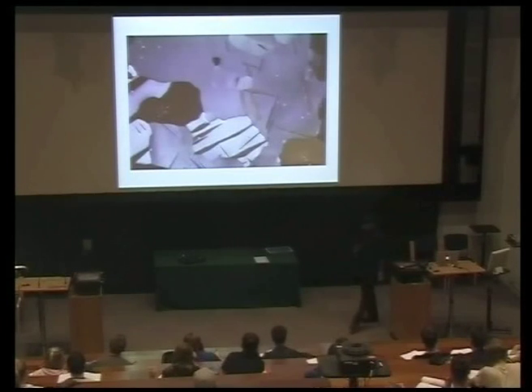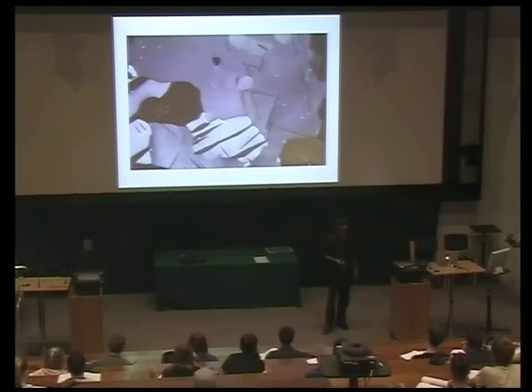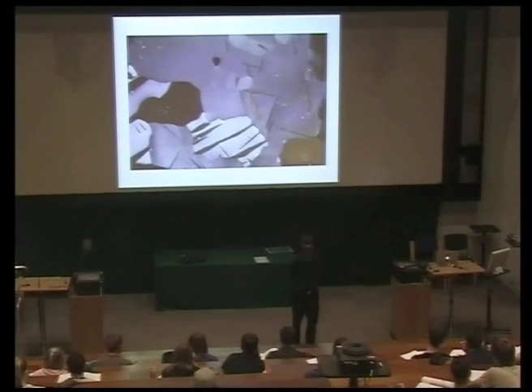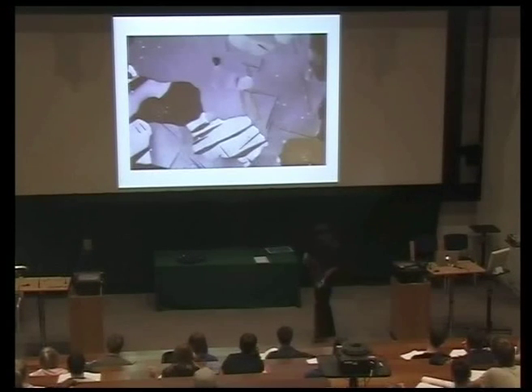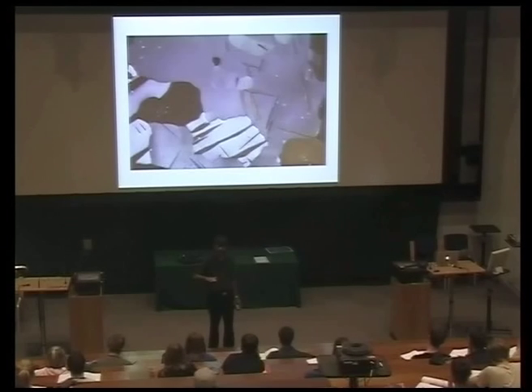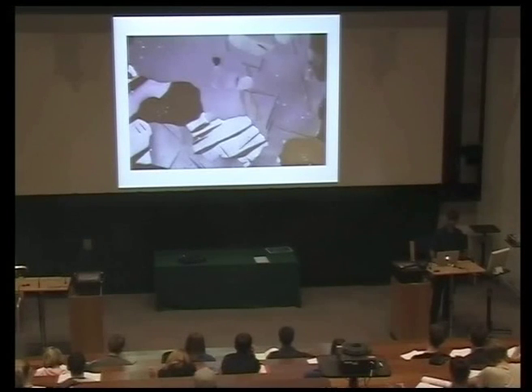Can you guess whether this is a mechanical twin or an annealing twin? What feature would you look at to identify it as a mechanical twin? Sharp tips. Look at the sharp tips here — so these are mechanical twins. If you polished this sample completely flat, mirror finish, and then twinned it, you would also see the displacement of the surface when the twin forms, because a mechanical twin is a deformation just like slip. In slip you see slip steps; here you would see the shear.